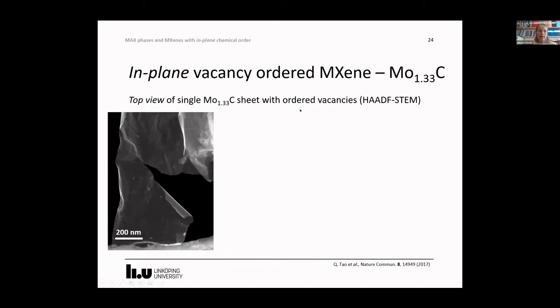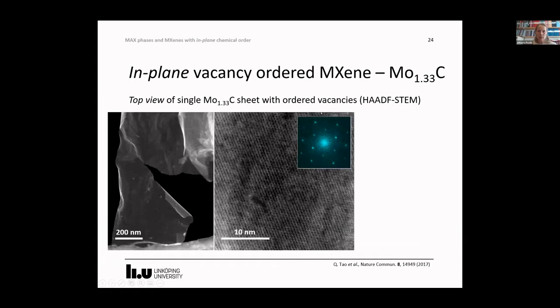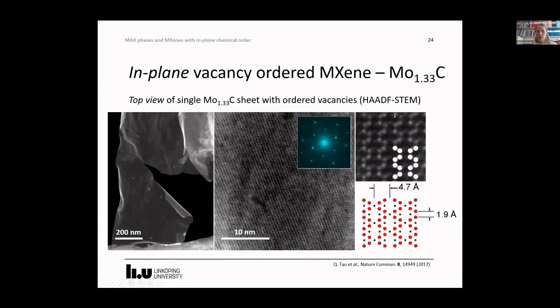Here we see a low magnification image of a single flake with dimensions below 1 micron. Here is higher magnification with a fast Fourier transform of this image, and this reveals a hexagonal-based crystal with these chain-like features, which means that we have the ordered vacancies. And here is a more zoomed-in structure where we see this even more clearly.